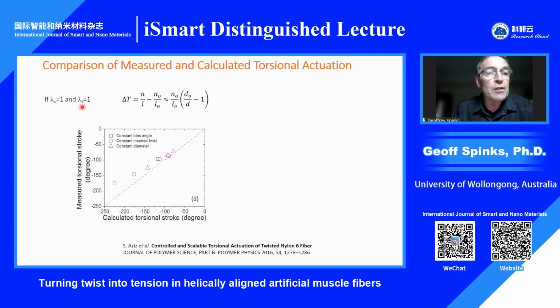So with these two assumptions and observations, our expression for the change in twist becomes really simple. It's just the inserted twist multiplied by the change in diameter of the fiber. And so we set about trying to determine whether that was predictive. We made twisted nylons with different amounts of inserted twist. We heated them and measured the rotation in a free rotation experiment. So it was just held at one end and heated, and we measured the rotation. We then calculated the torsional rotation based on the above equation.